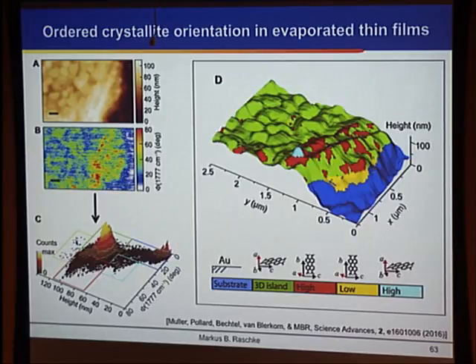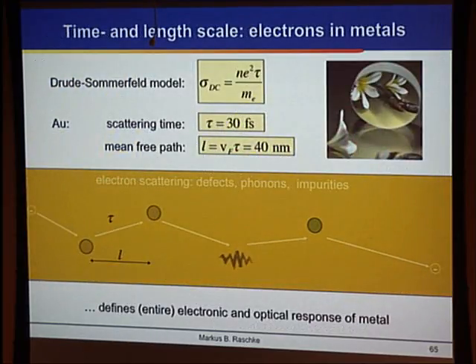Yeah, okay. So I'll show you then, I want to loop back to what I showed in the beginning, that one of the elementary processes of the electron dynamics is in metals, where you have this extremely fast scattering time and these extremely short time scales. And so this was really a challenge for us to say, can we actually really see this? Can we visualize the effect of carrier scattering and the associated dephasing of a coherent excitation on this time scale with that corresponding length scale, and then really see elementary interactions of the optical excitation in a metal.